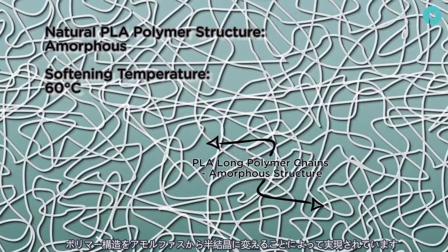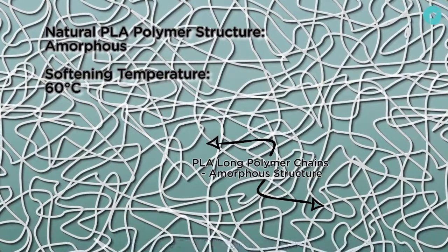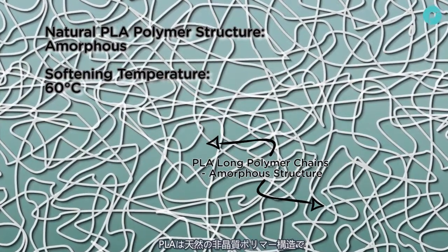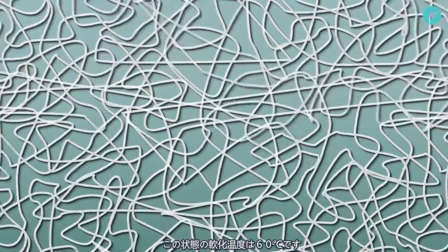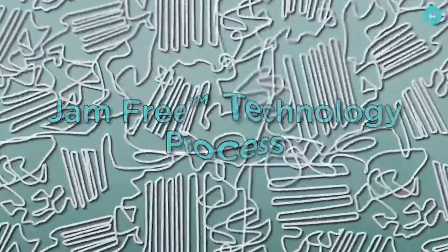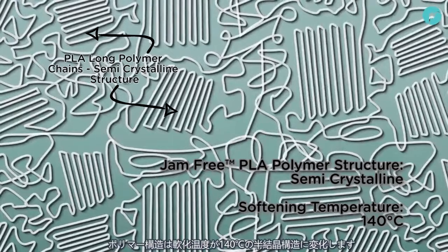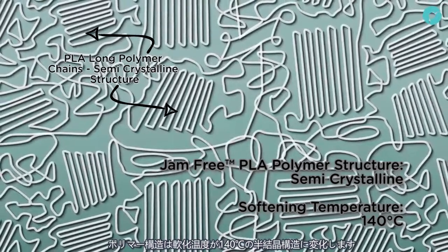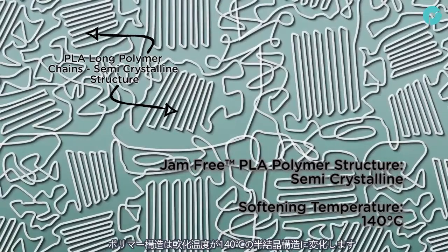Jam-Free technology works by changing the polymer structure from amorphous to semi-crystalline. PLA is naturally an amorphous polymer. During this state, the softening temperature is 60 degrees centigrade. After Jam-Free technology, the polymer structure is changed to a semi-crystalline structure. This raises the softening temperature to 140 degrees centigrade.